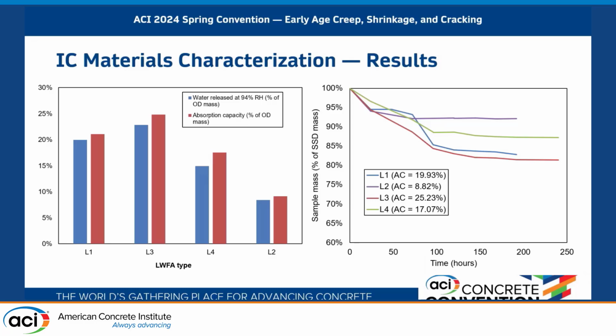And then we started comparing materials, again, on not only their absorption capacity, but also how quickly they lose that moisture when they're in a saturated condition, by putting them in an environment with controlled relative humidity. Because that is also important in selecting the materials for internal curing.